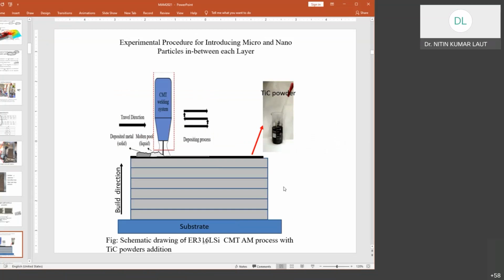So this is a schematic of how this is being deposited, and the powder we are using is titanium carbide powder, a nano powder, I think of 50 nanometer size. And this is our CMT torch, which you have physically seen in that setup, and that's how they are depositing. One layer, then the second layer, and then the third layer. So the movements are like this, but ensuring that you are getting the desirable interpass temperature.